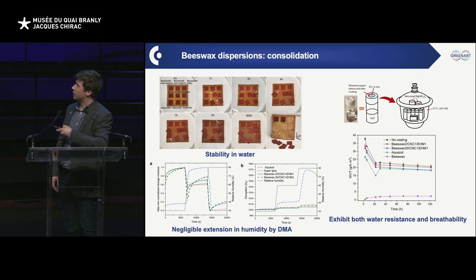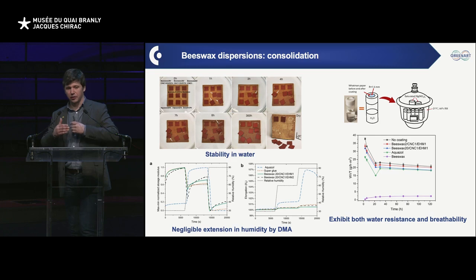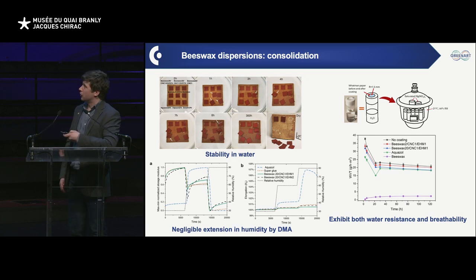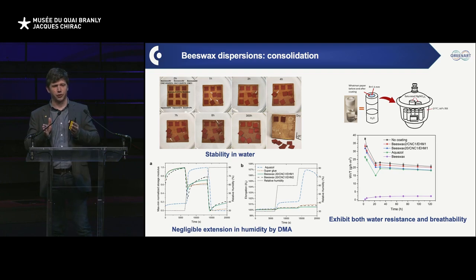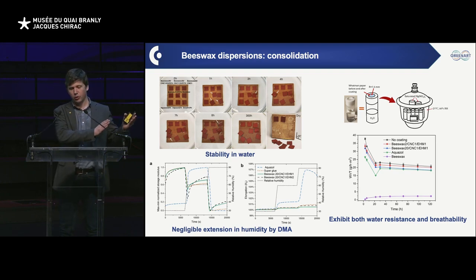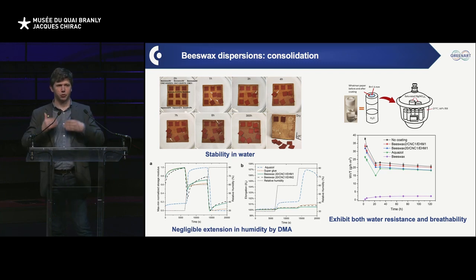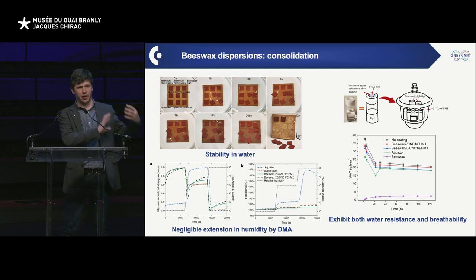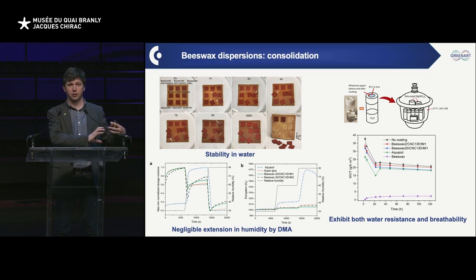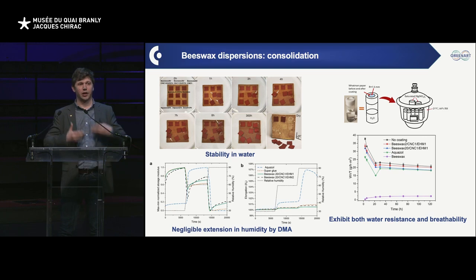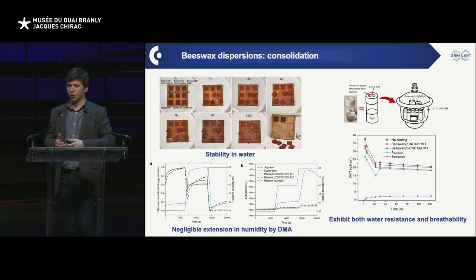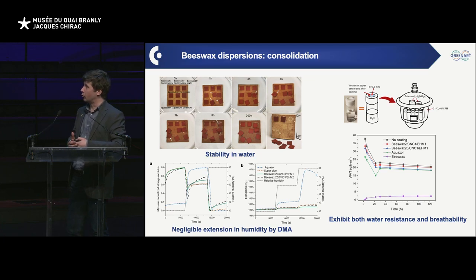And very rapidly, as time passes by, we can see that some of them are getting detached progressively. At the end of the day, what made us very happy is that the only two that remained attached after 300 hours were our beeswax formulation that contains the cellulose derivative, the EHEC, the CNC and beeswax. And that was the one that we're really boosting. So if we only use the beeswax as such with the cellulose crystals, this is not enough because the system is still too hydrophilic, even though it's 90% beeswax at the end when it is dry. We need to have this cellulose derivative that will accommodate and arrange itself to make things go the way we want.